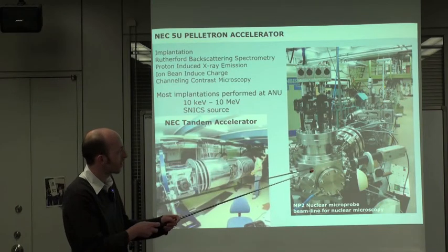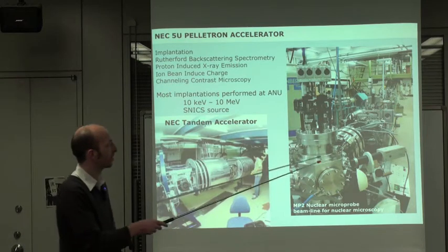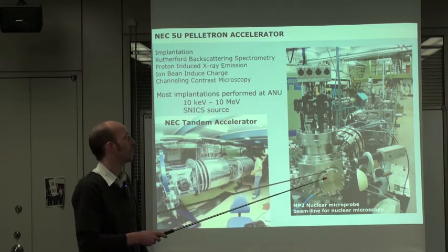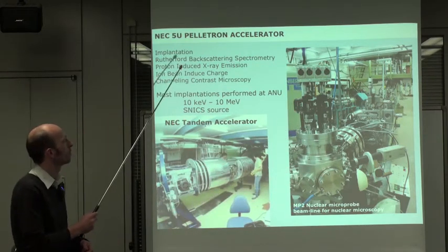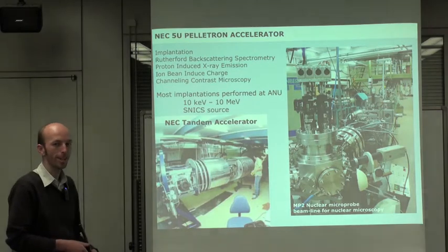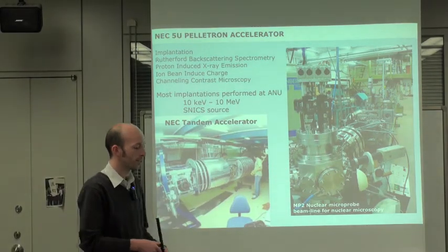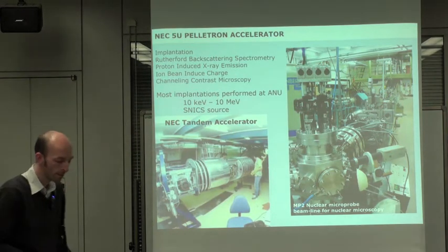We have a spot size at the chamber of under a micron, and we use this for various techniques. We can do implantation with it, but we also do a lot of Rutherford backscattering spectrometry, and we look at the charge collection efficiencies of our devices as well.